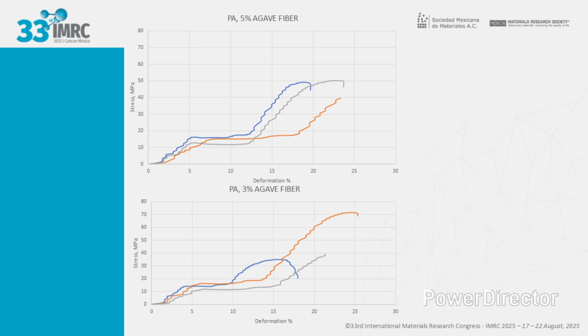Behavior with 5% agave fiber. The maximum stress reached is observed to be between 40 to 50 MPa. The strain at break is around 20 to 23%, indicating that the material retains some ductility despite the reinforcement. The three replicates show a similar trend, suggesting a relatively homogeneous distribution of fiber in the polymer matrix.